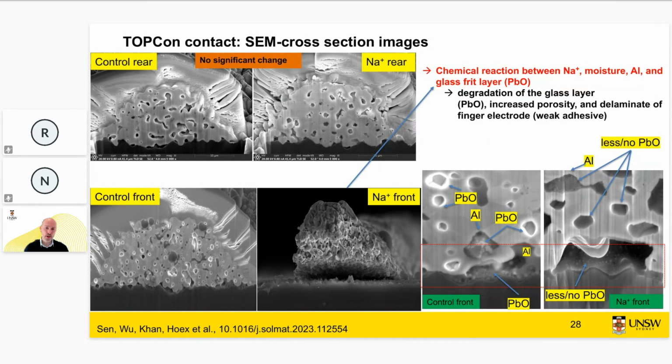And the sodium chloride also interacts with the lead oxide. And that's still something we see. These contaminants reduce the lead oxide to lead, and lead oxide is a key component in the contact formation. So one problem is now solved with laser assisted firing by the removal of aluminium, but still the lead oxide is a sensitive point.